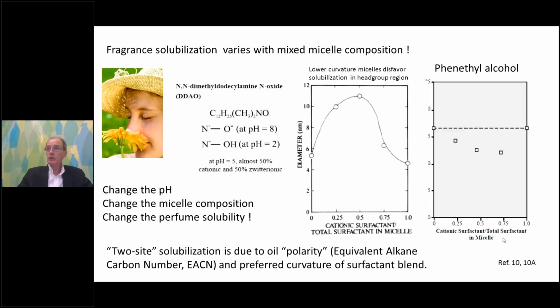And because you want to have nice smelling fragrance type wipes and lotions, we should realize that fragrance composition also varies with an amine oxide, for example, micellar solution, because the mixed micelle composition is varying. So here's the solubilization of phenethyl alcohol on the right here as a function of the amount of cationic surfactant in the total micelle. Phenethyl alcohol smells pretty nice, sort of smells flowery to me. It's a typical fragrance type component.